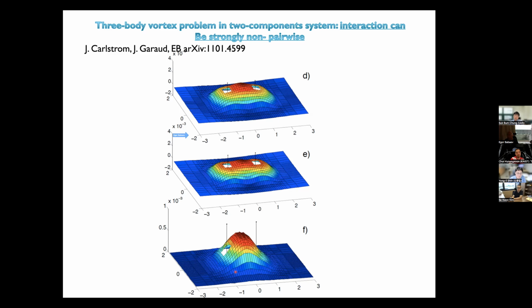Is this strong enough to change phase boundary significantly? Could you please say again? So is this non-pairwise interaction strong enough to change phase boundary from the classical picture? Yeah. So this does not, in the cases that we know at least, change the phase diagram, but it affects the structure of the vortex cluster.